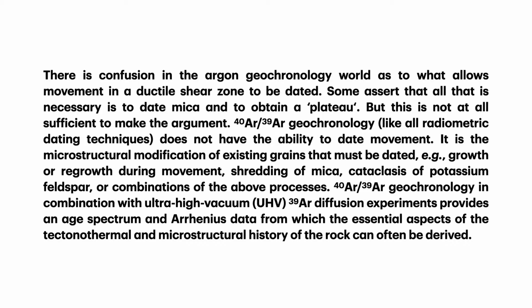Some people say that all you need is mica and you hit it with a laser and you get a plateau. But this is not at all sufficient to make the argument. In fact, we'll show that this is not the way to go. Argon geochronology, like all dating techniques, does not have the ability to date movement. It is the microstructural modification of existing grains that must be dated. For example, growth or regrowth, shredding of mica, cataclasis, or combinations.